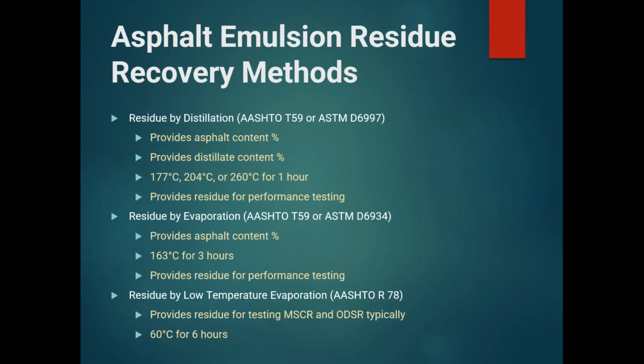The rest of the tests we're going to discuss are done on the actual residue of the emulsion itself, so just the asphalt portion that you want to recover. So there's three basic ways that we recover residue from an asphalt emulsion. The first one is called residue by distillation. This is the quickest way to recover asphalt residue from an emulsion, and it's typically performed at either 177, 204, or 260 C, and it takes about an hour.